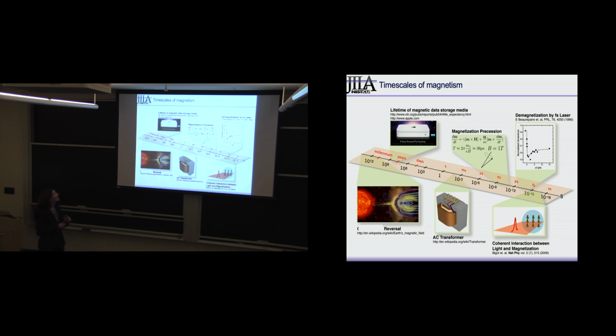Correct. Exactly. So let me give an example of how we fell over this technique by looking at how fast one could switch a magnetic material. For a very long time, people thought that the fastest dynamics in magnetic materials were associated with the precession of spins, so on picosecond to nanosecond time scale. And then about 22 years ago, when ultrafast lasers became usable by other people, Jean-Yves Bigot and Eric Beaurepaire did an experiment where they just shone a femtosecond laser on a magnetic material and saw that the magnetism quenched in an incredibly fast time scale. And so the question was, what's going on?